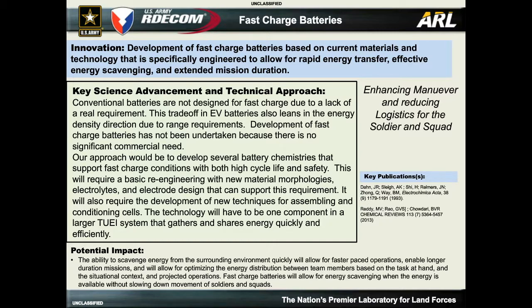The second approach is to change the type of anode material that you use. So if you can use lithium titanium oxide, LTO type materials, or other newer anode materials that allow for fast charge, that's an approach that's been taken by certain battery manufacturers, and that again allows for fast charge in the order of minutes. Okay, and then the third approach is really looking at new electrolytes that will allow for fast charge acceptance at graphite anodes. That's the most preferred approach, but also probably the most difficult approach.